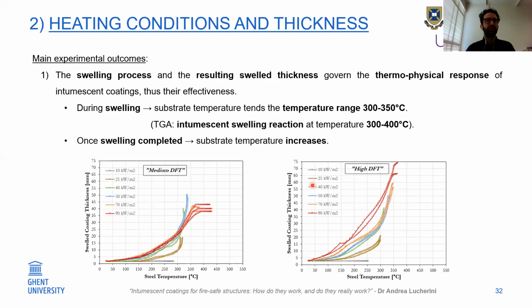And in terms of conclusions, first of all, the swelling process and the resulting swell thickness govern the thermophysical response of intumescent coatings. Because, for example, if I compare the steel temperature with the swell coating thickness, you can see that when the coating starts swelling, all the temperatures tend to the same range between 300 and 350, but then at a certain point start increasing above 350 with the same thickness.